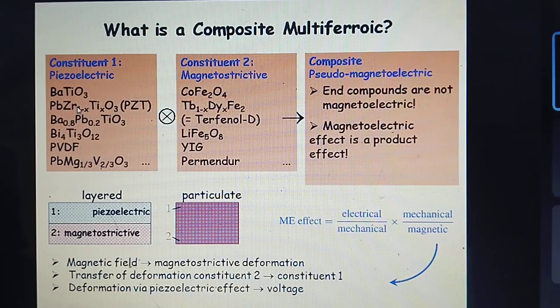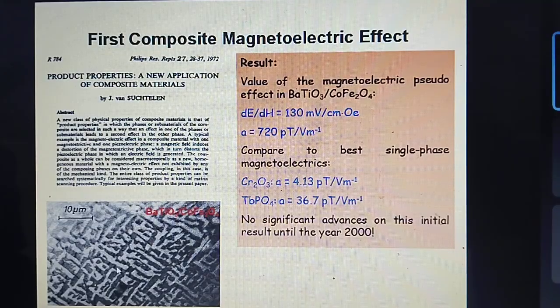That means you have to mix in such a ratio that the properties of the charges and the properties of the magnetic domains should remain over here. So you can also see here, you have a particulate where the first layer is a piezoelectric, second is magnetostrictive, that is a magnetic material, and this is a ferroelectric material. Right. This is the report of a paper published in Philips Research Reports during 1972. The first composite magnetoelectric effect was observed in a material of barium titanate / cobalt ferrite, which I was talking about.